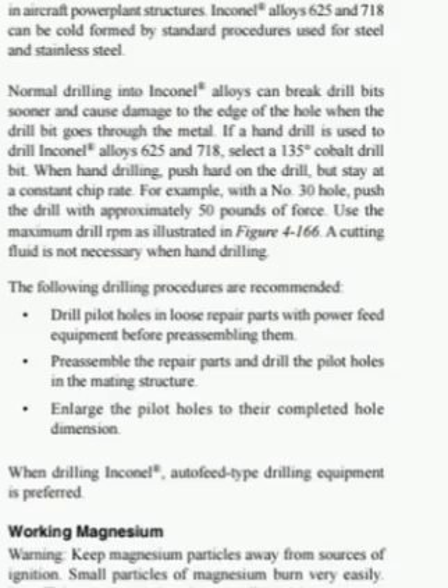Normal drilling into Inconel alloys can break drill bits sooner and cause damage to the edge of the hole when the drill bit goes through the metal. If a hand drill is used to drill Inconel alloys 625 and 718, select a 135-degree cobalt drill bit. When hand drilling, push hard on the drill, but stay at a constant chip rate. For example, with a number 30 hole, push the drill bit with approximately 50 pounds of force. Use the maximum drill RPM as illustrated in Figure 4.166. A cutting fluid is not necessary when hand drilling.